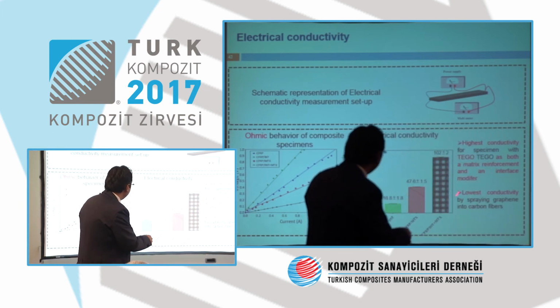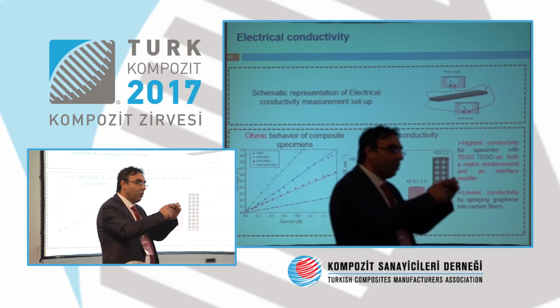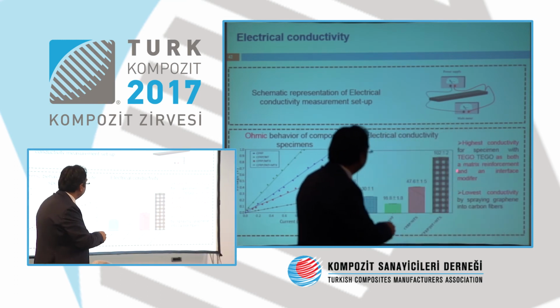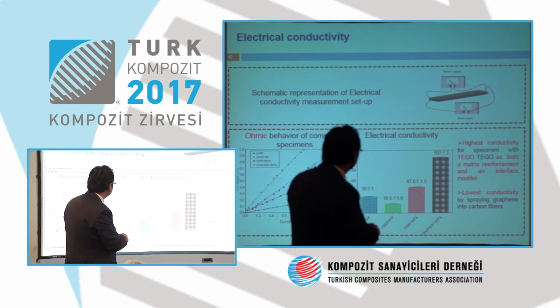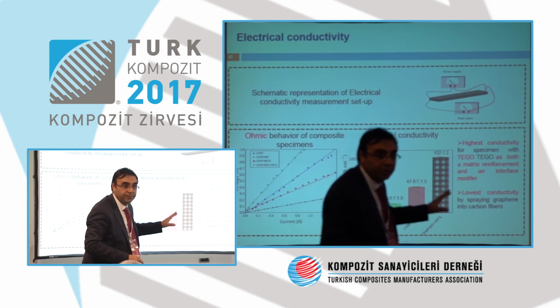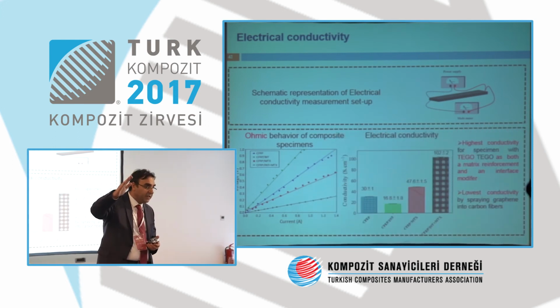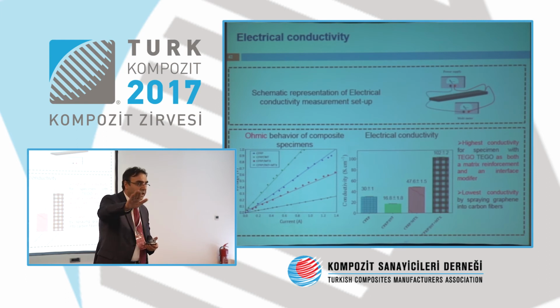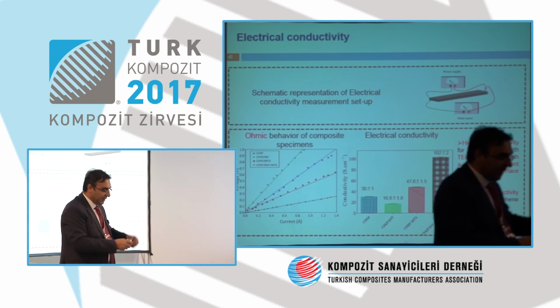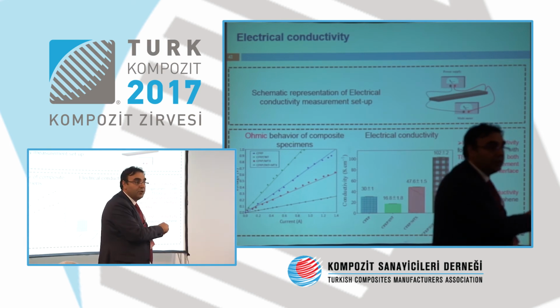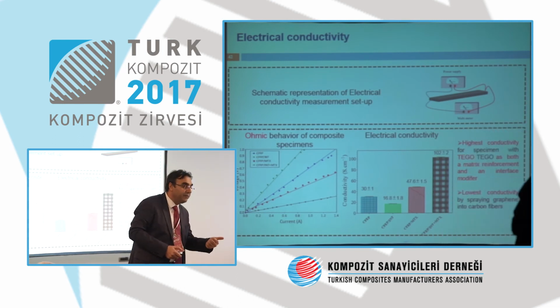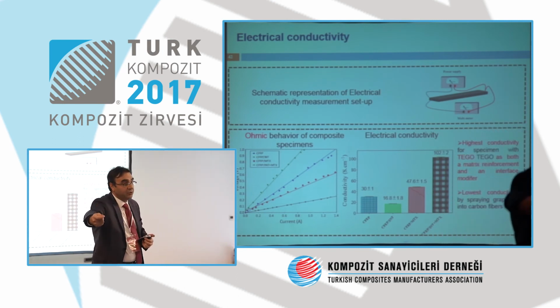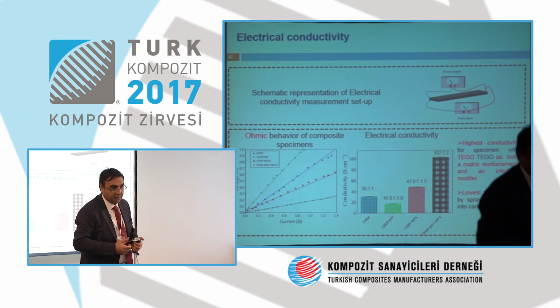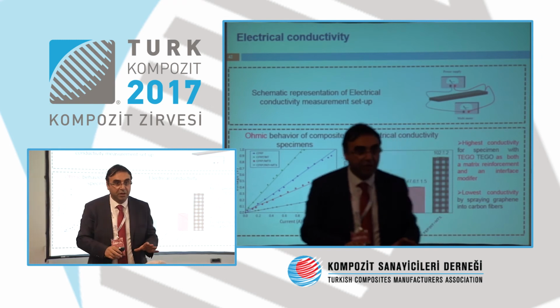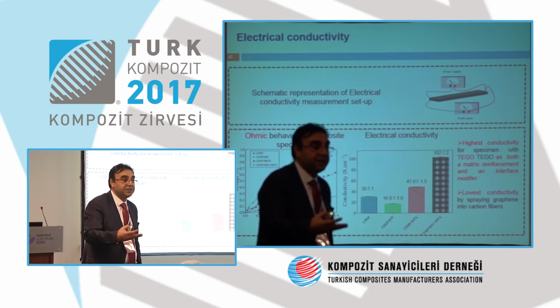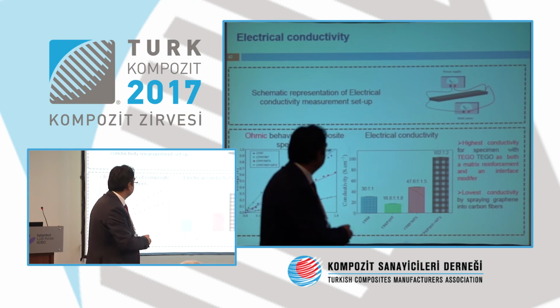But what we observed, if we use the hybrids, by combining TEGO with the matrix, is that you can increase your electrical conductivity performance almost 4 times. That is huge, because for aircraft applications, for lightning strike, they put a mesh onto the skin of your aircraft. Instead of putting a mesh, because that is the amount of conductivity required, you can integrate this one. It is going to act as a reinforcement, and as a pathway to discharge the lightning strike, so that your laminate is not going to be damaged. So this is, I think, one of the highest results reported in the literature in relation to this.